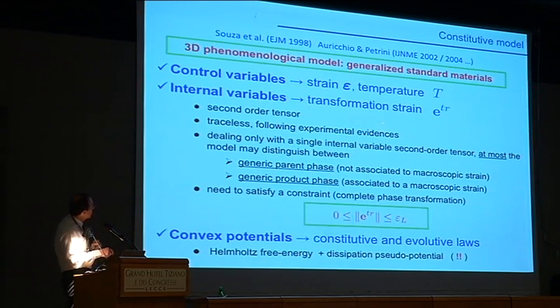This internal variable should naturally satisfy a constraint, because since we are dealing with a material which undergoes a phase transformation, this variable cannot evolve indefinitely. It cannot evolve forever. So it should satisfy some constraint, and the constraint is indicated here. Basically, the norm of this internal variable should be bounded above by a material property, ε_L. Which means that the material can either be in the situation where the norm of this variable is 0, or it can transform. But once the full material is transformed and oriented, you cannot proceed with more transformation. So it should be bounded.